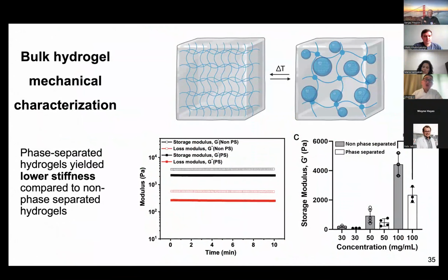autofluorescent cases. So now we wanted to test out the mechanical property of the hydrogel. So we basically generated hydrogels that are non-phase separated and phase separated. And interestingly, with the idea of having the particles in the gels, we thought we would be able to get a higher stiffness. Surprisingly to us, across the concentrations, we always find that the phase separated gels have a lower modulus, which is shown in the solid domains here.